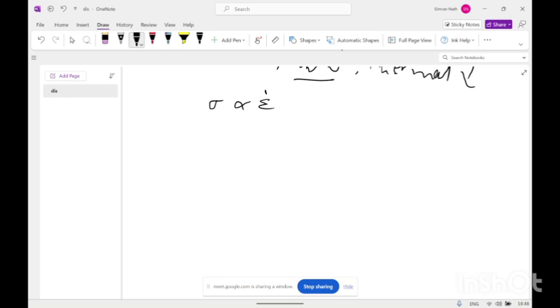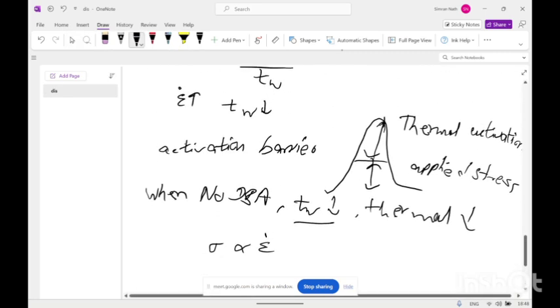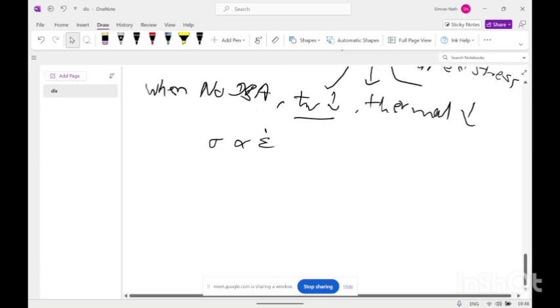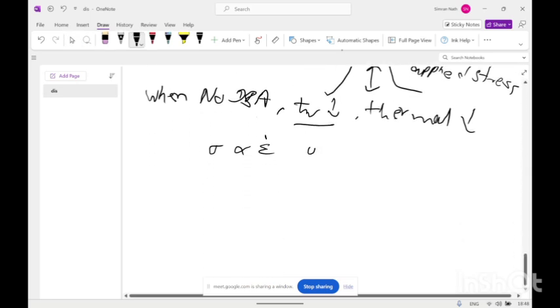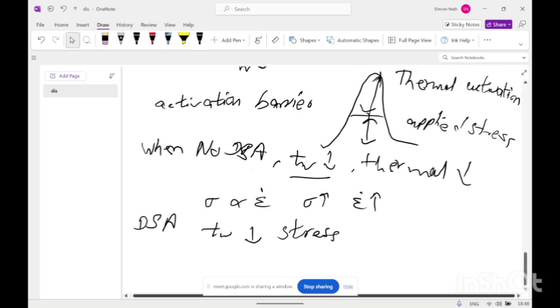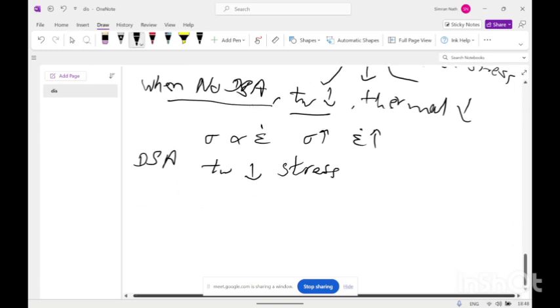So in this case, when there is no DSA, stress increases with increasing strain. While in DSA, as the waiting time decreases, the stress to move the dislocation will decrease also. It means when there is no DSA, there will be less effect of solute atoms, while in DSA, dynamic strain aging, the effect of solute atom pinning will be higher.